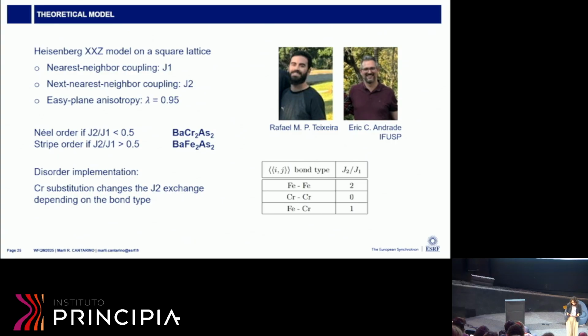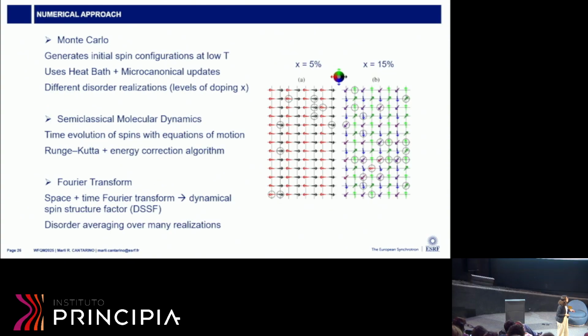With this simple model, on top of that, there is a numerical implementation with Monte Carlo. So there is an initial spin configuration, and then there are updates of the initial configuration, and different disorder will have different degrees of doping to reproduce the actual impurities and chromium doping in the material.